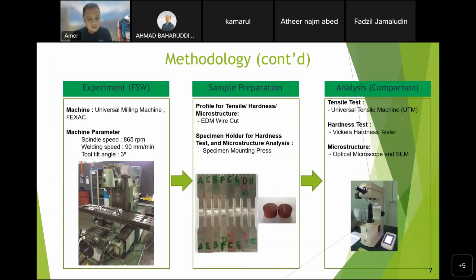So this is the flow of the experiments. Start with the friction stir welding process, then the sample preparation, and the last one is the analysis. For the friction stir welding, I'm using a conventional universal milling machine. The fixed parameters for the friction stir welding process are spindle speed 865 RPM, welding speed 90 mm per minute, and tool tilt angle 3 degrees.